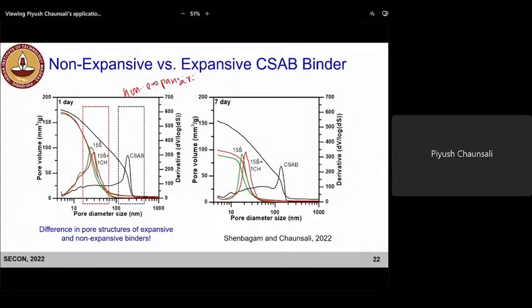What we noticed is a clear difference between the non-expansive system and the expansive system. So this is the CSAB cement by itself, which doesn't expand, but upon adding extra sulfates in the form of gypsum and calcium hydroxide, you see the shift in the peak. So the critical pore size reduced in expansive cementitious systems. We saw that as early as 1 day, and also at 7 days. So this was the differentiating factor between non-expansive binders and expansive binders.